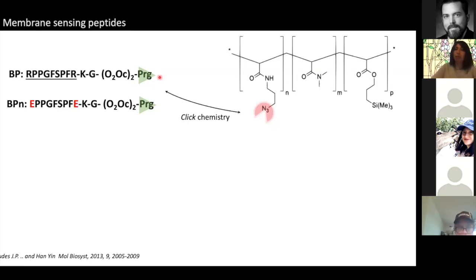with high chemoselectivity to the surface of microarrays by the use of a polymeric coating, by a click chemistry reaction. Basically, this polymer coating is able to provide on the surface of microarrays azido groups, this one, that can react with high selectivity with the alkynes of the propargyl glycine.